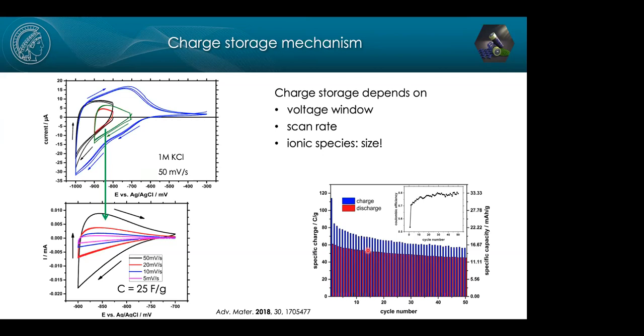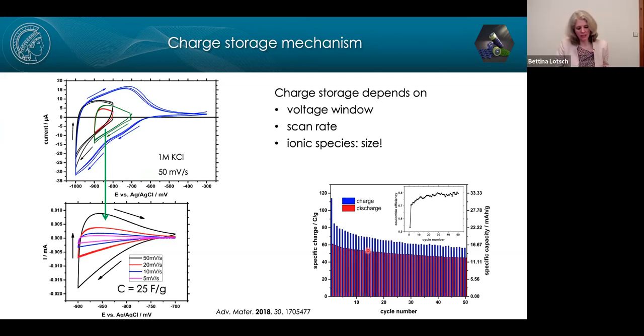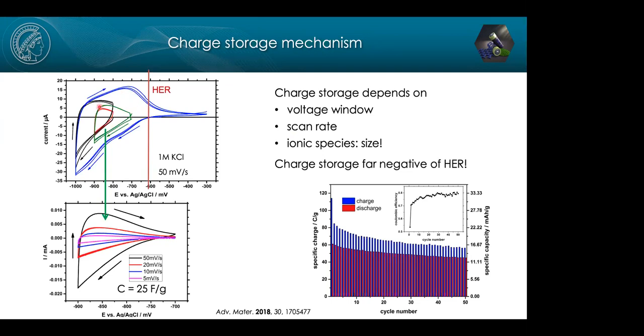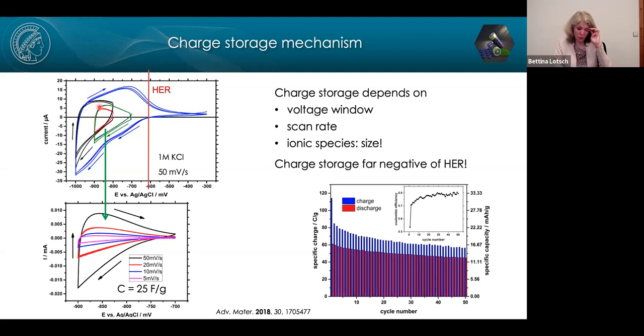Now, the point that I really want to reiterate is that charge storage in the system, as you can see here, occurs way negative of the hydrogen evolution potential. And that again tells us that this is a system that can be operated in water in principle, and where hydrogen evolution does not really interfere, ironically, in these systems. So this might be a system that is interesting for aqueous solar batteries, perhaps.